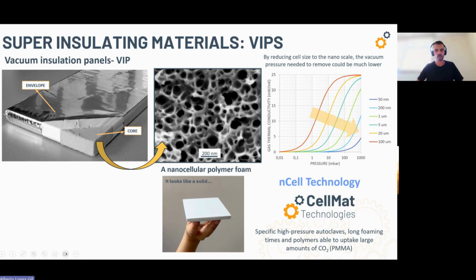We have been able to produce nanocellular polymer foams that are very promising for this application. The cell size is below 200 nanometers. So what you see is like a solid panel. So you don't perceive this material as a foam. But if you look at the micrograph, at the microstructure inside, you see that this is a foam. This is a technology that we have developed.